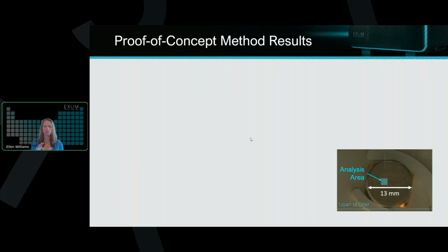And then we experimented with different laser powers as well as analysis areas. We also will typically do a cleaning run where we do a first layer pass of ablating the surface layer, removing that from the quantitative results, and then average across several areas below that cleaning run. So that's what you can see there on the analysis area. All of this process, this method, took about 15 minutes per sample. So again, much easier than digesting your powder in acid for ICP techniques, and again, able to get those metallic and oxygen numbers in the same analytical session with the same technique.